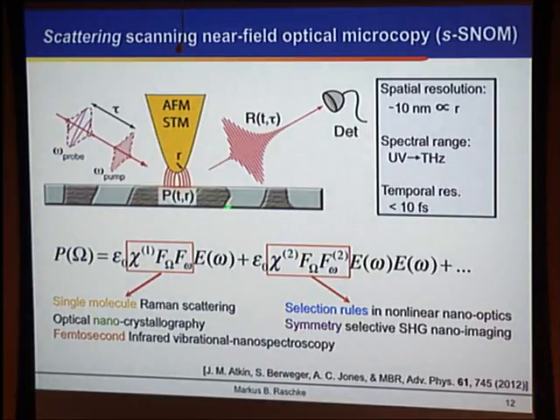And then when you look at the response of the coupled tip-sample system, you can reconstruct essentially the local material response, whether it's in linear or nonlinear order. Here's again sort of a summary of the parameter space we can access. We can get about 10 nanometer spatial resolution, in good cases down to maybe 5 or even 3 nanometer. We have the full wavelength range covered over all relevant milli-eV to electron volt interactions, and then we can do this with extremely fast time resolution. I'll show you an example in the end.